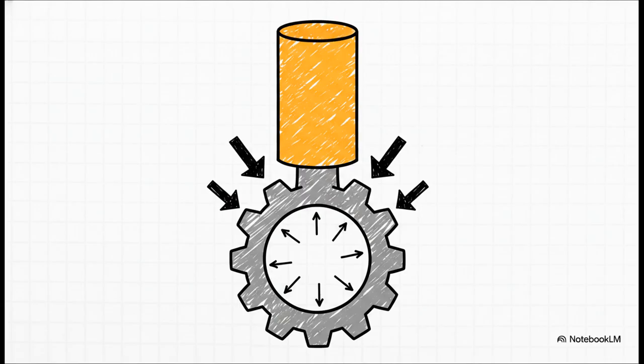A riser is basically a sacrificial pool of extra molten metal that's connected to the main cavity. By designing the riser to be a really thick shape, like a cylinder, it naturally has a larger volume-to-area ratio than the main casting. And because of Chvorinov's rule, we know the main casting is going to solidify first. As it shrinks down, it simply draws still liquid metal from the hotter riser to fill in any gaps, ensuring you get a flawless final product.